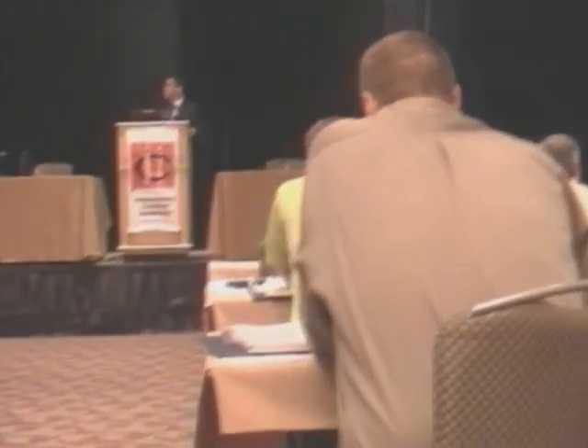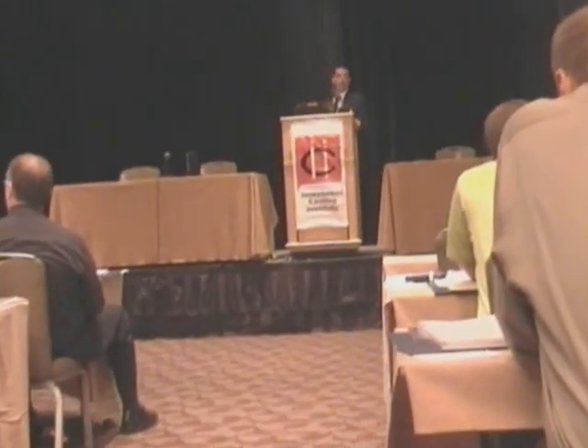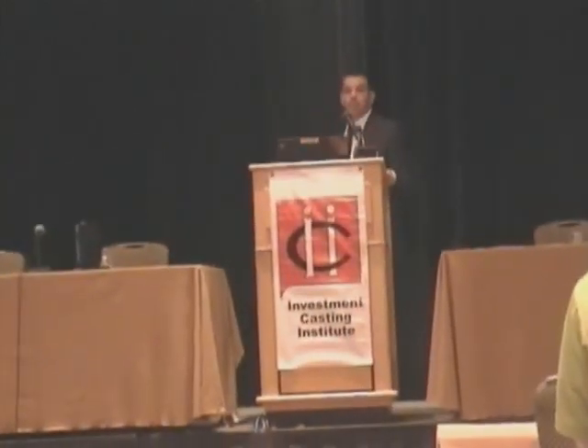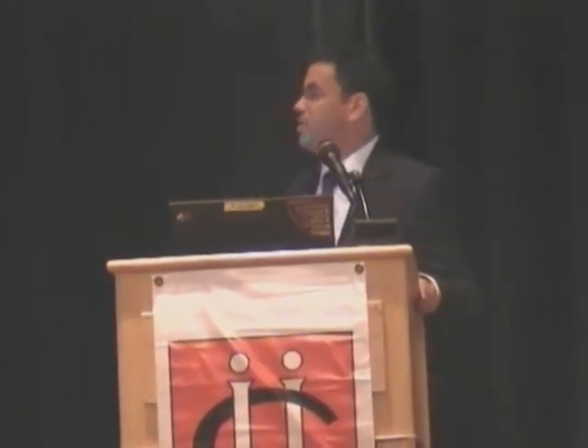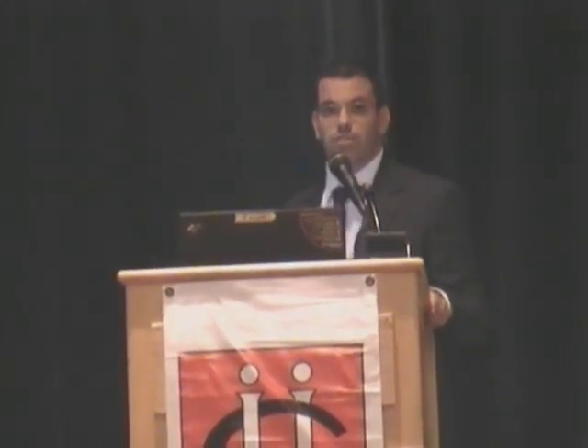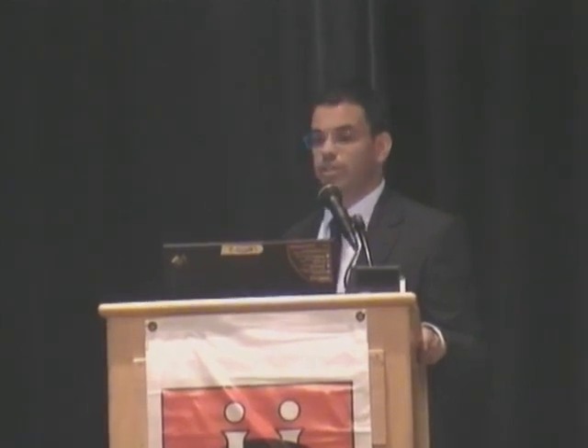Now they're drying better. They drain better, much easier to process, much easier to clean. Obviously drying off half of the gates or even less. And most importantly, it gives us an easier view on the casting behavior. So now we know if those parts get micro shrinkage or gas porosity, then we should go and check the process. Somebody didn't do the degassing process properly, maybe they are out of argon. Nobody knows. So, achieving the first 2 C's.